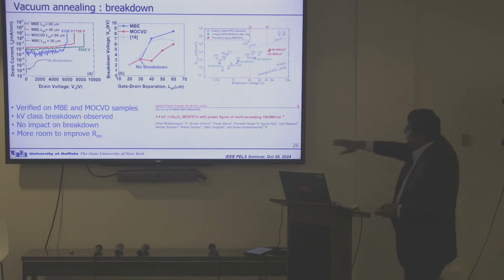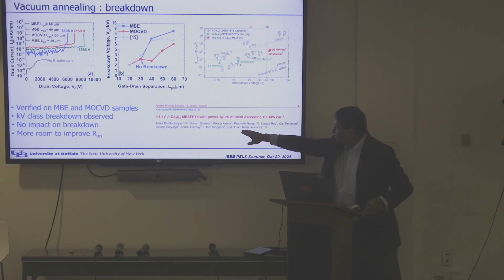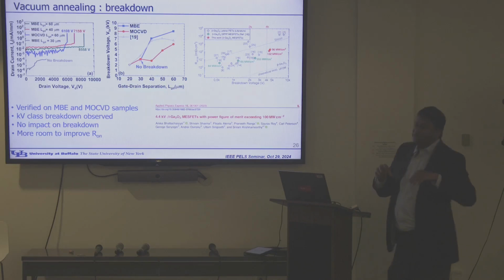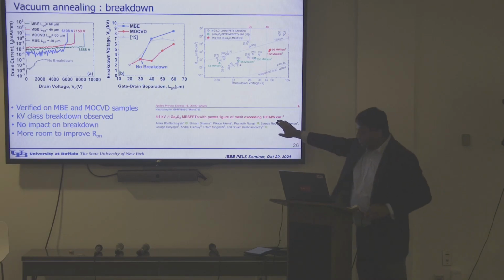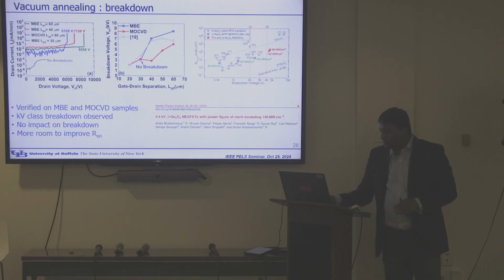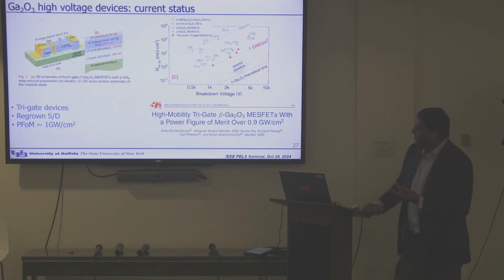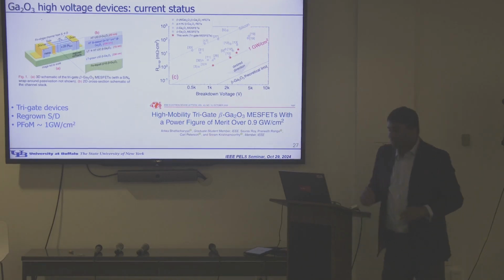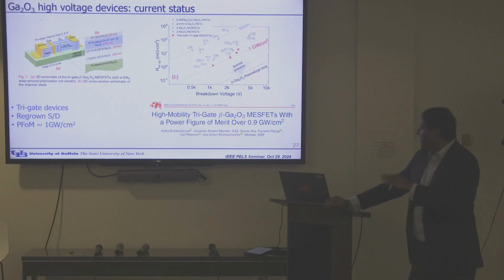We also measured 4.4 kilovolt MESFET device. This is by Sriram Krishnamurthy's group, where they use the regrowth of the source drain regions instead of the RIE, so they get good on resistance also. So just the status, I would say that again their group has shown that we can actually get 1 gigawatt per centimeter square of figure of merit for a single device. Again, it's very impressive, as you see on this chart here. People have shown 10 kilovolt devices using lateral MOSFETs in gallium oxide.